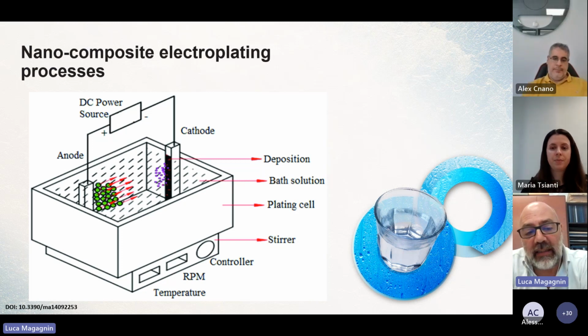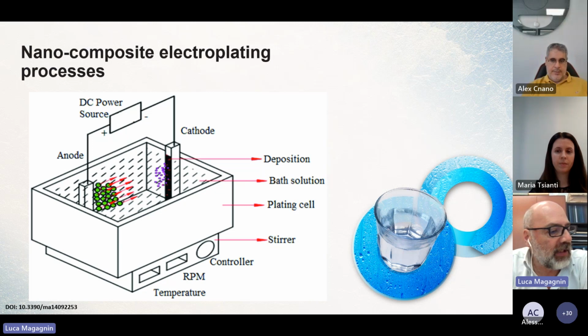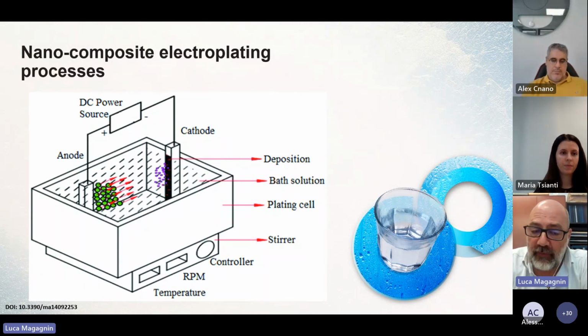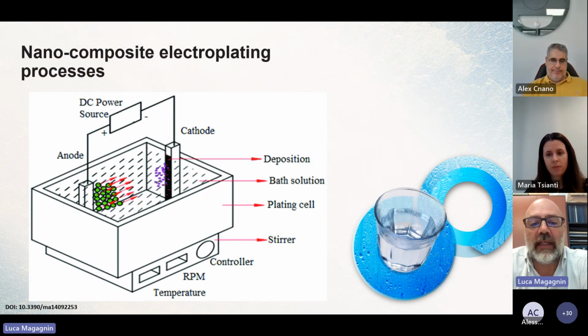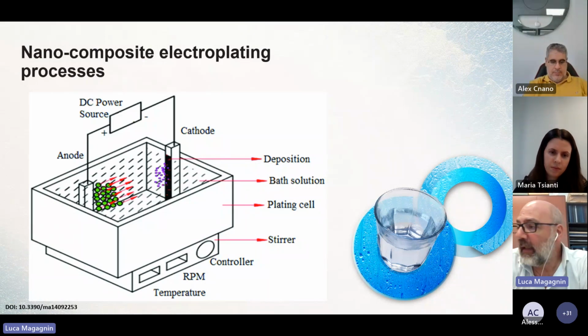But actually, what you see here is the presence of the particles. In this picture, we can say the green or violet particles represented here. And so here is the major issue in this kind of approach, because our aim is to find an alternative to hard chromium, which means that the coating should have very high values of hardness, for instance, and these values of hardness should be homogeneously present in the overall part of the component. That means that the particles which contribute to the increase of hardness should be very uniformly distributed into the layer, into the coating, into the matrix. And so there are two major aspects, the amount of particles and the distribution of the particles.